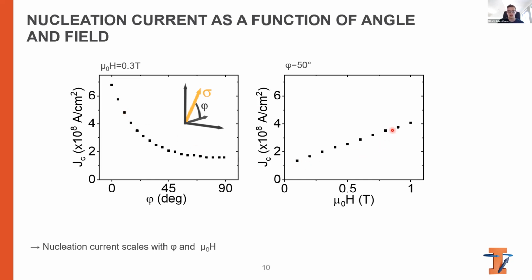And then with higher magnetic fields, we also need a higher current, so a higher spin injection, because at higher fields, the moments are more rigidly coupled to, or more rigidly in the direction of, the magnetic field. So we need a larger torque and therefore a larger current in order to tilt them away from that direction.